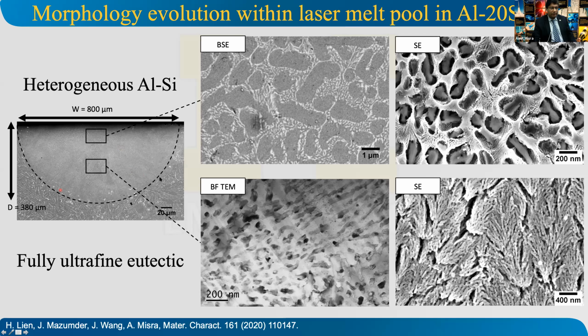So this is a cross section of a laser melt pool where you see heterogeneous structure starts to form. The interesting thing is the composition does not change. So we started with a hyper eutectic, 20% silicon, realizing there might be some silicon loss because of vaporization and so on. And the goal was to produce something that is closer to eutectic structure.